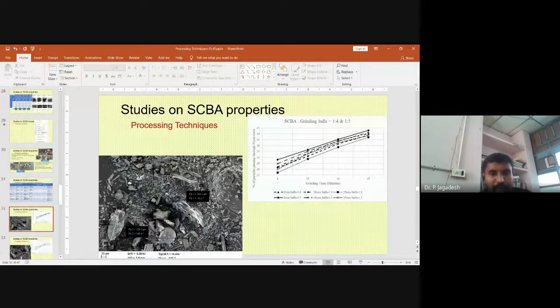The optimum size in each process is shown in the last column. Then under each process, the morphological change observed is shown in this slide. For example, if you take SCBA to grinding ball ratio as 1:4 and 1:5 for different size of balls, you can see the maximum percentage of particle passing through 40 micron sieve is higher for 8 mm balls with 1:5 ratio.